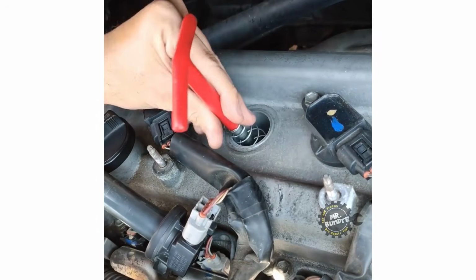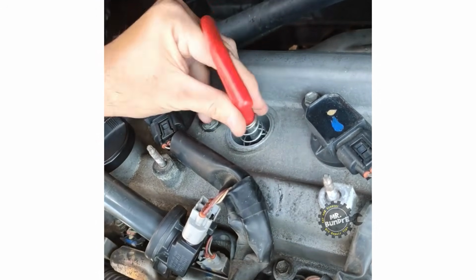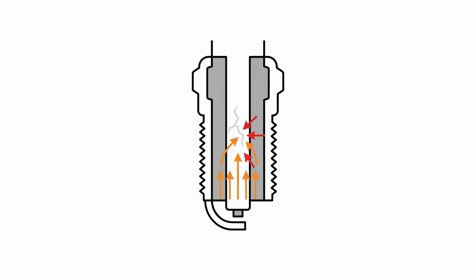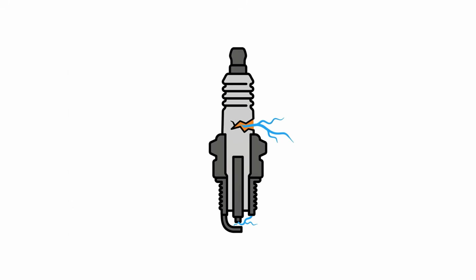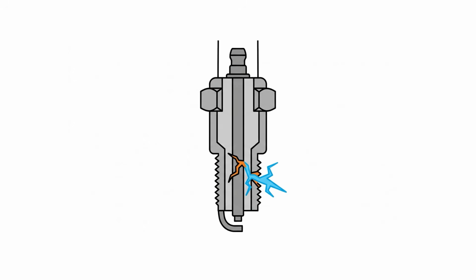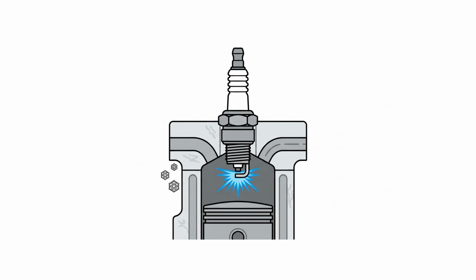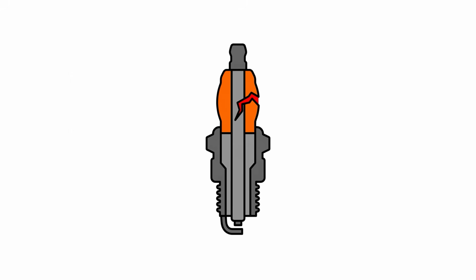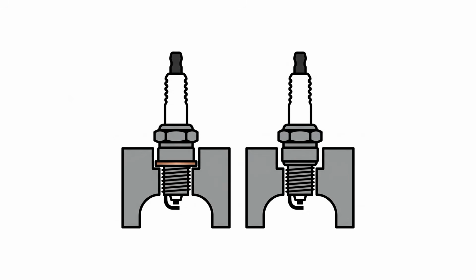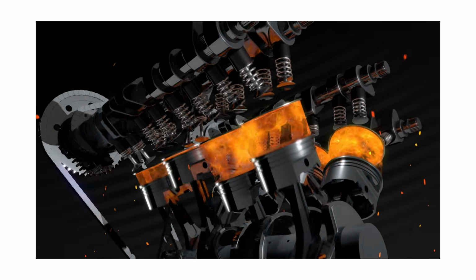That plug now has an invisible fracture inside the ceramic. Under extreme heat and pressure, that crack propagates. As it opens, it creates a new path for spark energy to escape. Instead of jumping the electrode gap, the energy leaks through the crack. The plug fires perfectly cold. Once the engine reaches operating temperature and the ceramic expands, the crack opens. Misfire. Let the engine cool, the crack closes, plug fires fine again.